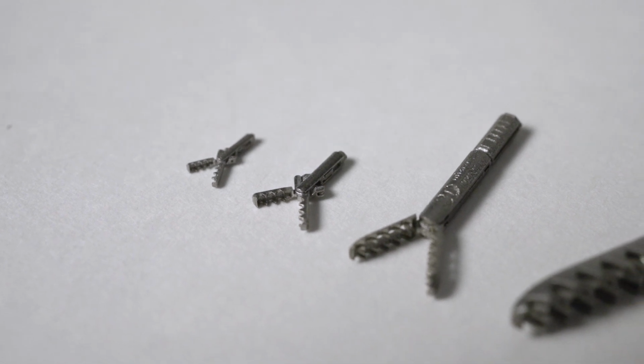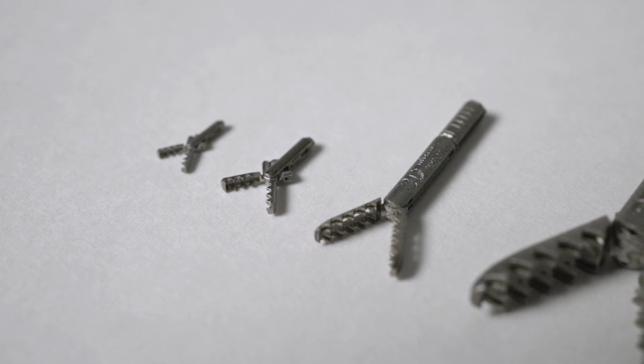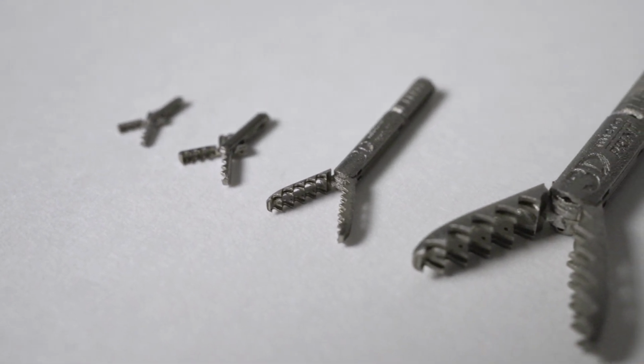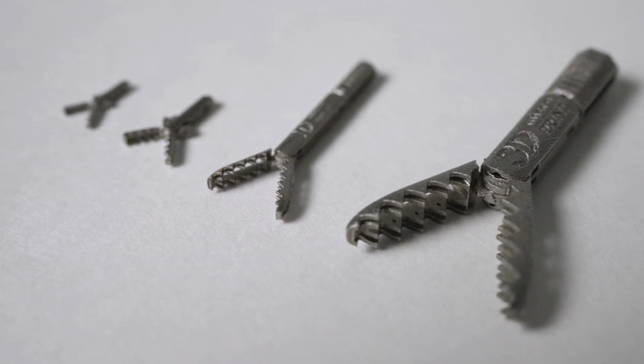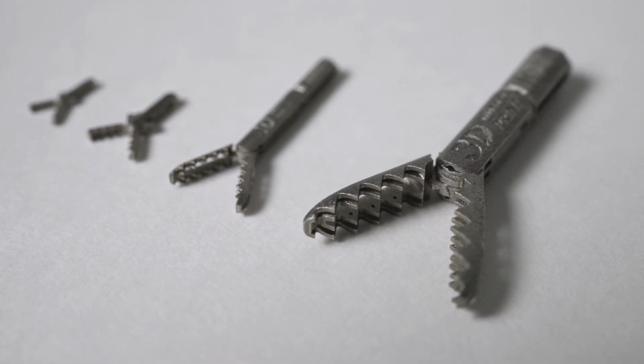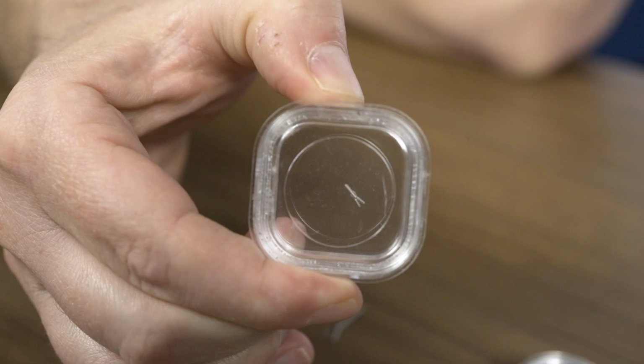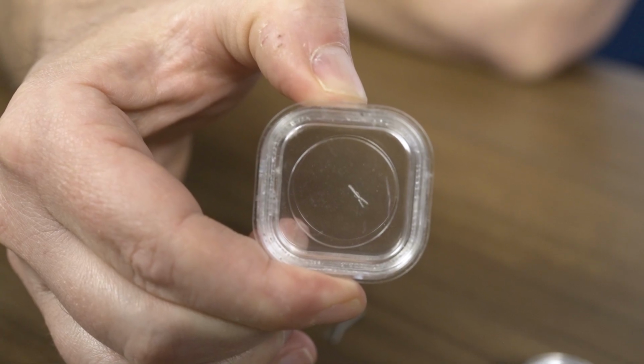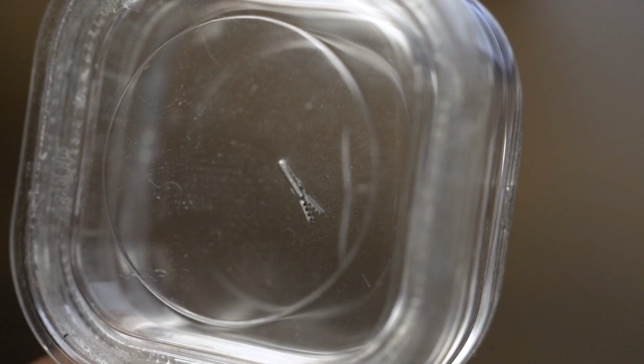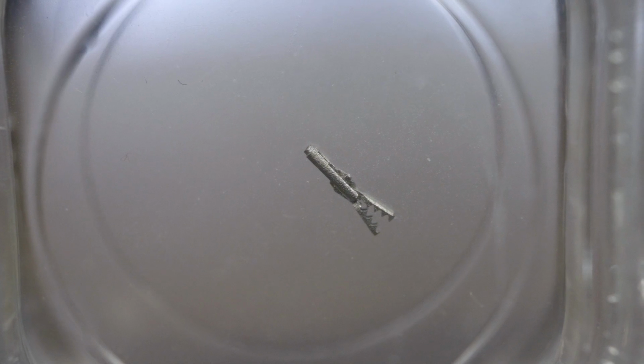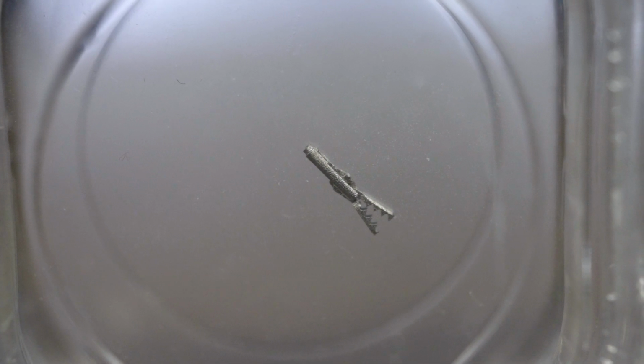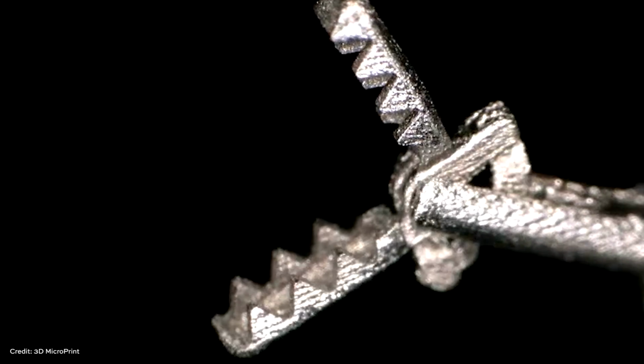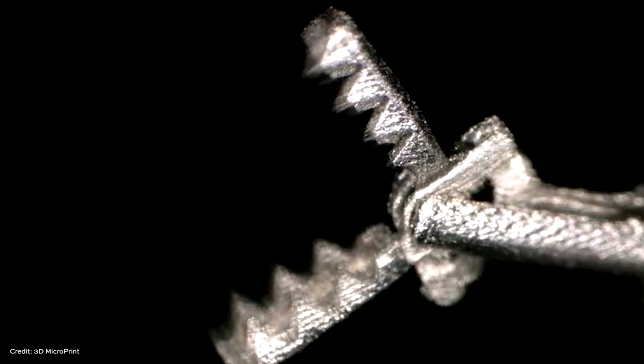We do the grippers in several kind of geometries for direct customers. They are used for surgical robots or for handheld devices. So we can add also any kind of surfaces to the gripping surface of the device itself, and we can do separate variable sizes of them. Actually, we have the gripper in a dimension, the smallest one at 800 micron diameter. So it fits to a 0.9 hollow needle, taking biopsies. And the recent request is to get them down to a diameter of 600 micron. So just to cut off a third of them.